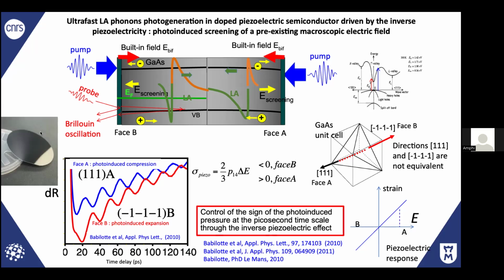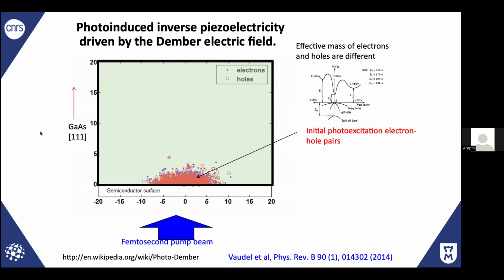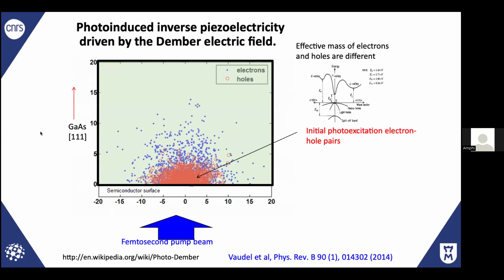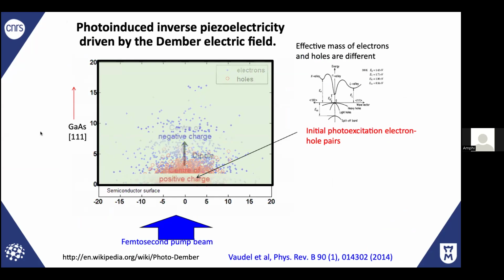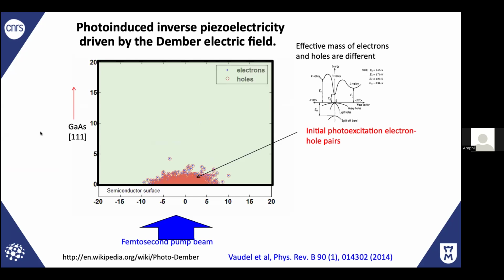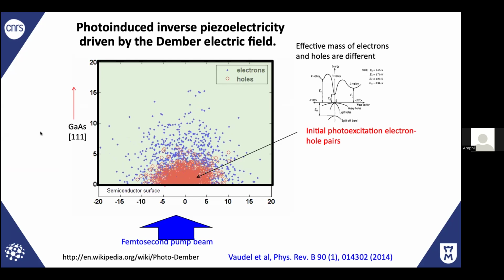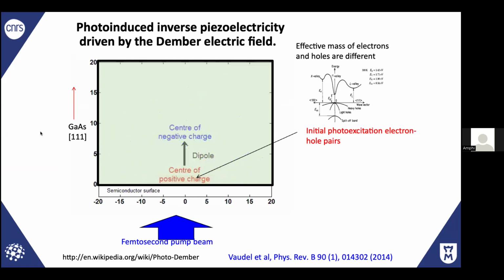Typically, here the optical penetration of the pump is 20 nanometer. So we control the lattice motion within the first 20 nanometer beneath the surface. Let me show you another situation with the Dember field. The Dember electric field works well in undoped semiconductors, so there is no band bending on the surface. When you shine light on such a semiconductor, because the effective masses of electron and hole are different, the diffusion coefficients are different. So electrons diffuse more rapidly than holes, and that creates what we call the Dember electric field.